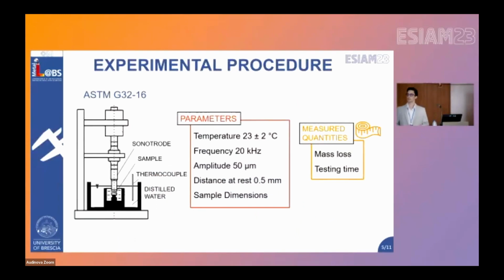And to characterize the cavitation erosion, we followed the American standard that employs a vibratory apparatus that you see in the sketch. The main component is the sonotrode. The sonotrode will vibrate at a frequency of 20 kilohertz with the tip immersed in distilled water at a fixed distance of 0.5 millimeter from a fixed sample. The vibration will generate cavitation of the liquid near the sample surface.